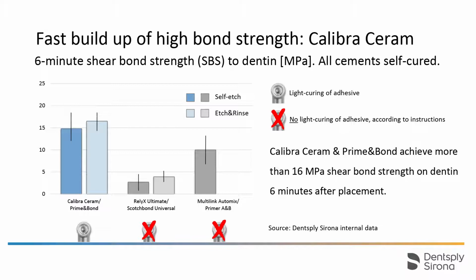Displayed are shear bond strengths in megapascal achieved by our product and competitors RelyX Ultimate and Multilink Automix. Prime & Bond active adhesive was light cured, while Scotch Bond Universal and Multilink primers A and B were not, as per manufacturer's instructions. Please note that Multilink cannot be used in an etch and rinse mode. As mentioned, all cements were self-cured. The specimens were debonded after 6 minutes.